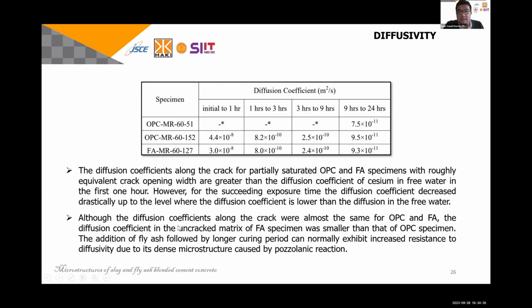And for the next, we also calculate the diffusivity along the crack. As you can see here, the OPC and fly ash specimens result in an almost similar diffusion coefficient. So we can conclude the diffusion coefficient along the crack for every specimen is almost the same. It depends on the liquid itself. So here the diffusion coefficient along the crack is independent of the specimen, whether you use fly ash, slag, or only OPC.